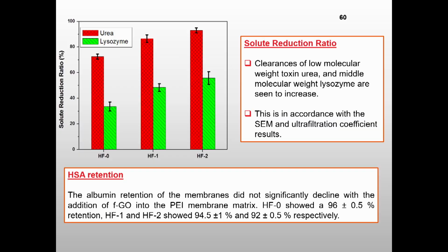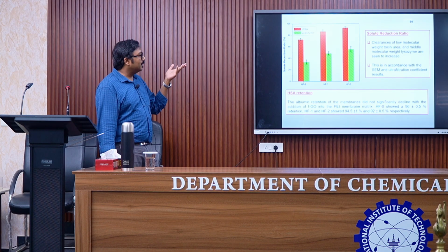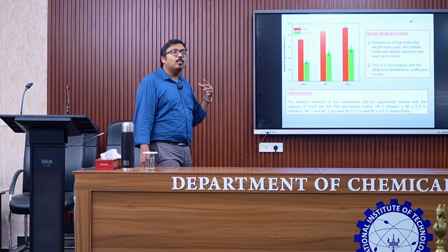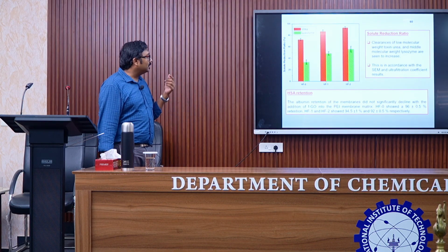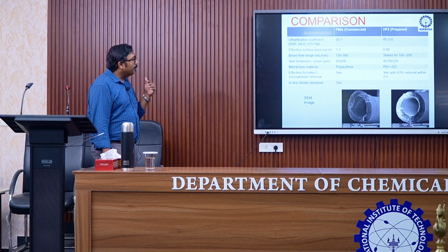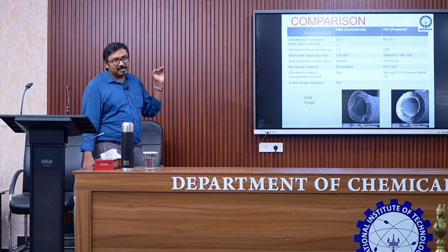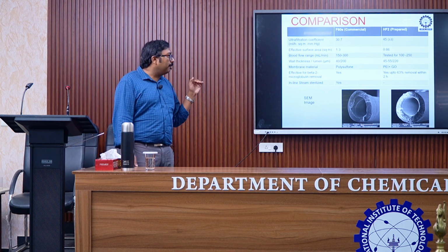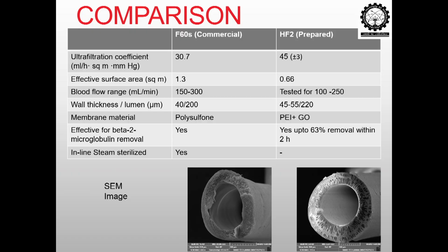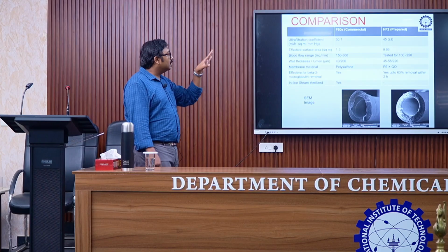For urea and lysozyme, we checked the reduction in 3 hours. Within 3 hours you have greater than 90% removal of urea, and lysozyme removal of more than 60%. This is what happens in a typical single run of dialysis as well. And we compared with F60S, the commercial Fresenius membrane that people now use in the market, that all hospitals use. And this is what we had prepared.